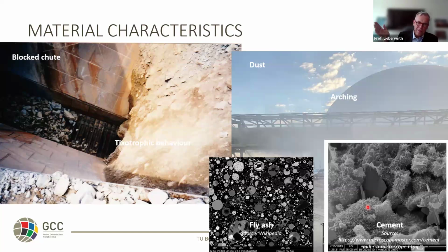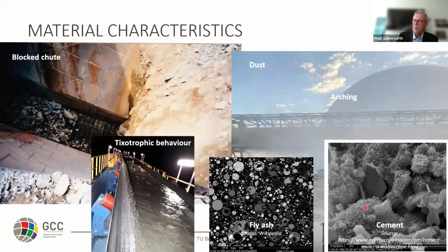If you have an aspiration system, so bag filters, if you have too much air, if you suck too much air, then all your fly ash will end up in the filter. And if you don't do enough, then essentially it looks like on the picture here, where we have a lot of dust. And this is something you have to be careful about.